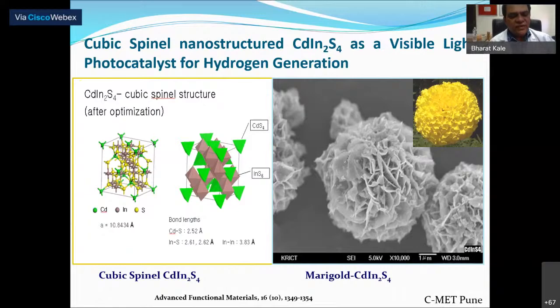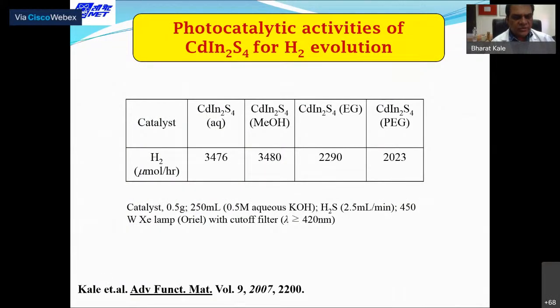This is the first catalyst we produced, with a marigold type of structure which gave good photocatalytic activity, about 2000 to 3000 micromoles per hour. We have also produced a flower-like structure as well as nanotube-type structures. Both give good photocatalytic activity.